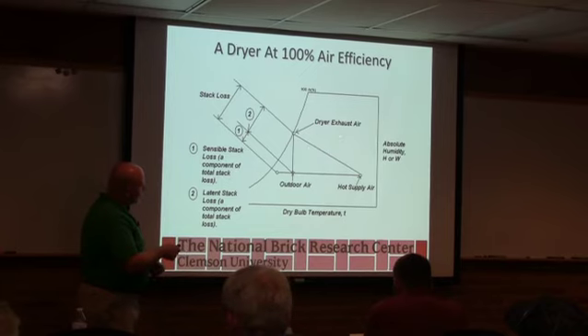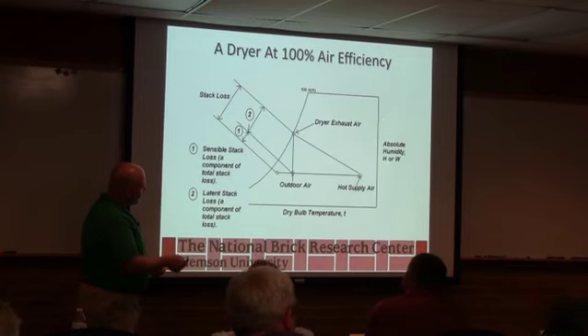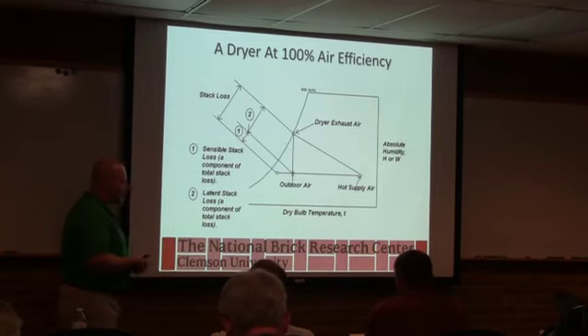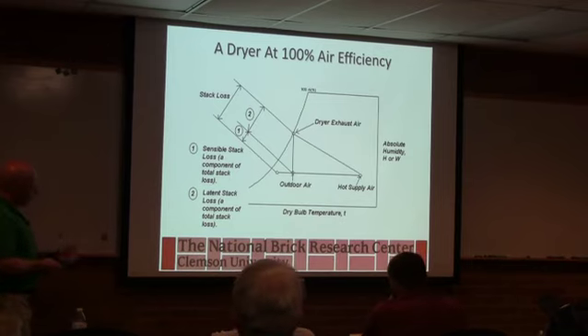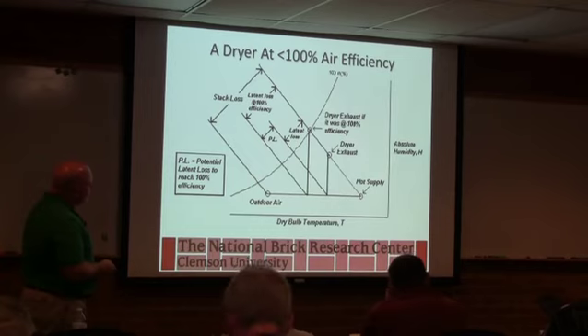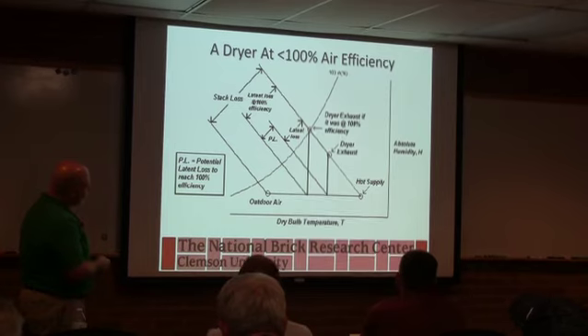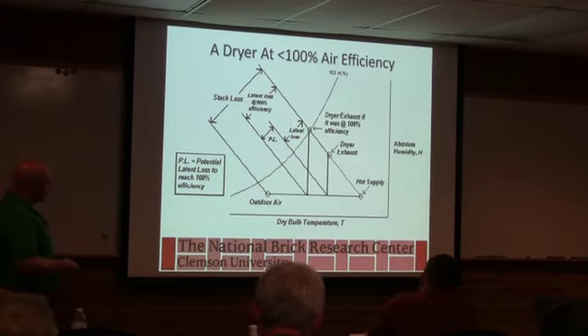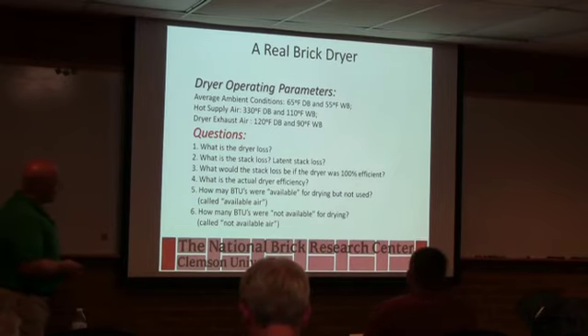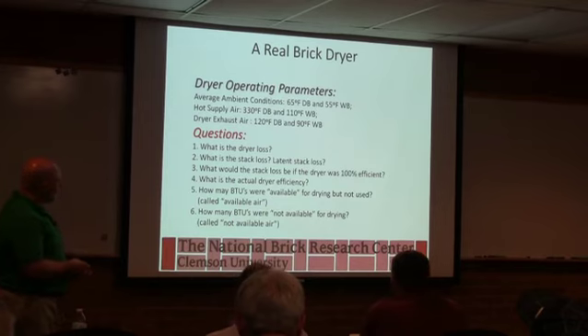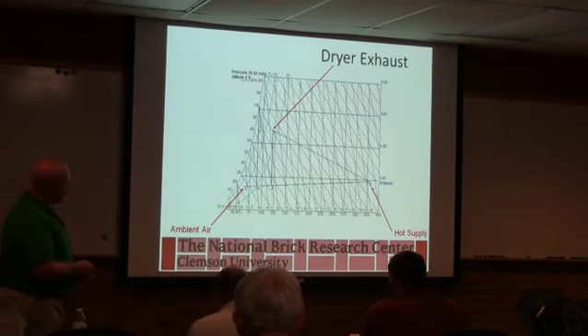And if you knew how to read the chart, basically this tells you the absolute humidity, how much water the air is holding on this axis. And I could read over, and by difference I could calculate how much water was exchanged from the brick to the air. And then in cases where you're not at efficiency, you can figure out basically how much energy is being wasted that could have been used for further evaporation, if you're that interested in breaking it down that precisely. But that's all in that "You Gotta Have Heat." You can see how to do that. This would be an example we could have worked through. If we had a little more time, I probably would have sat here and tried to work it out with you, but we're going to pass on that. But basically, there's a solution. So that's the first part of drying.